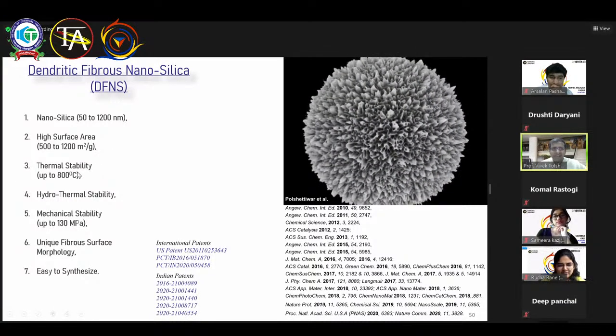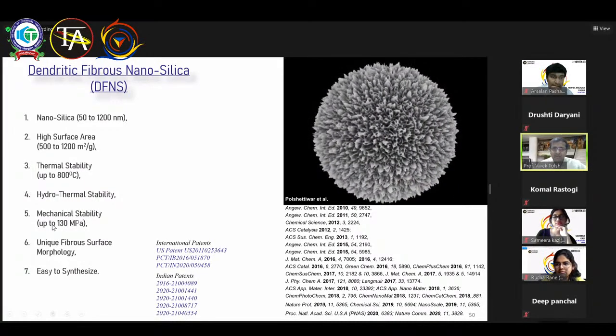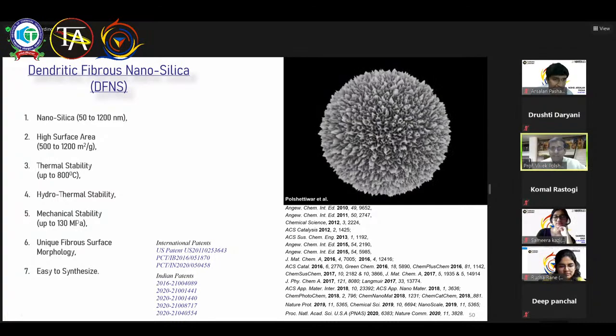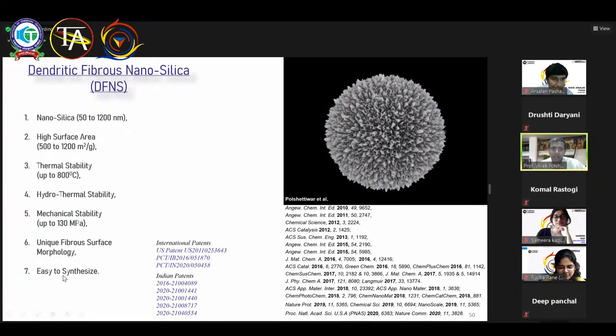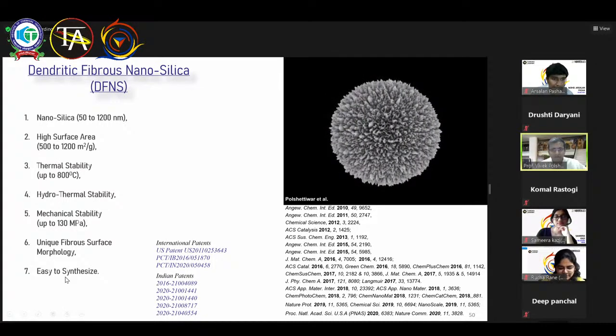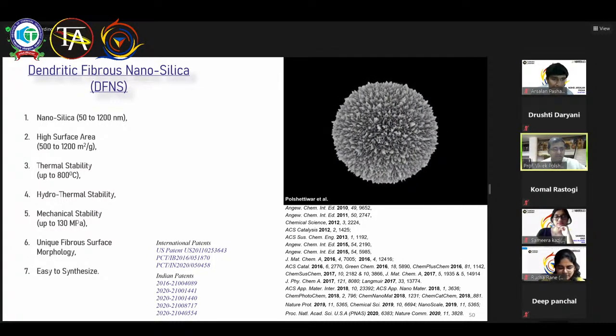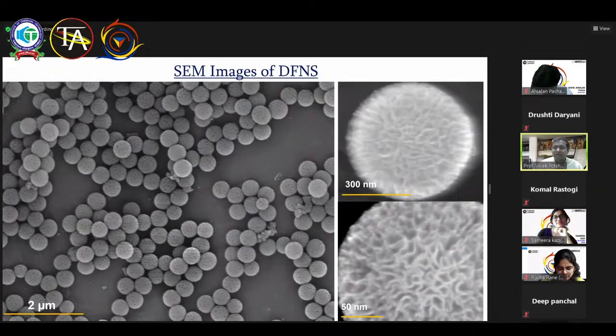Then they have several inherent properties like thermal stability and mechanical stability, so you can do high temperature and high pressure processes using these materials. And the most important thing is the synthesis. When we discovered it, we used some advanced technique to synthesize it, but recently we wrote this Nature Protocols paper where we showed that one can synthesize this material in any lab which has a round bottom flask, heating mantle and stirrer. So it's very easy to synthesize, and one can now synthesize on a larger scale. These are the SEM images, scanning electron microscopy images, indicating the monodispersed nature of the particles and their dendritic fibrous nature.